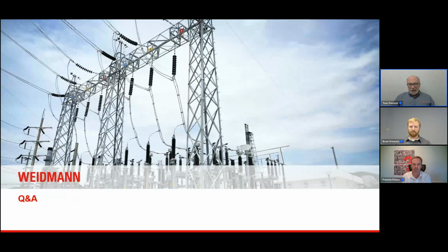And then specifically for high density transformer board made by Weidmann, that brand name is T4. And for low density transformer board made by Weidmann, that is called Hival. So when we look at these results, we can say for sure 100% that the thermal class of Weidmann transformer board is 120 degrees. We can't guarantee that for all other pressboard material. So I would say that still has to be determined by the manufacturer of those materials or a third-party lab.